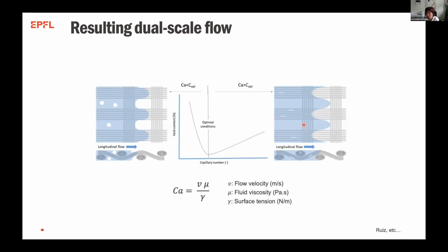So if I want to go really fast when I do impregnation, especially for RTM and so on, I may end up shooting myself in the foot, creating a lot of porosity, whereas I have to go at some nice optimal condition. And there are lots of works on how to find the optimal conditions using finite element models. If you know the optimal capillary number, you can adjust the pressure ramps in your part, and they've done a lot of this in Montreal, and it works really well. You can optimize at least the quality of your part while keeping the impregnation time decent, of course.